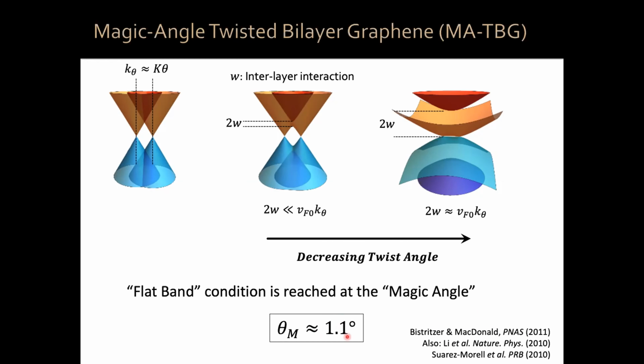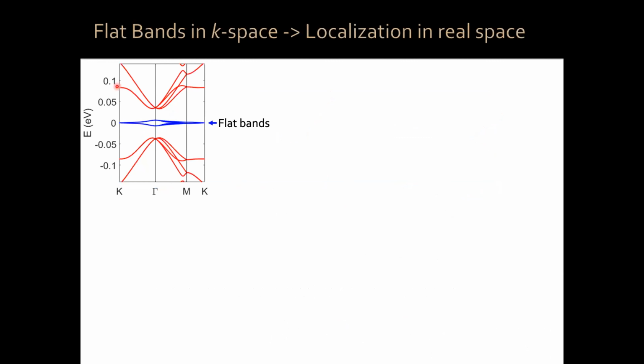Now, this is a magic angle for graphene on top of graphene. This depends on the materials. Yeah? Now, this is sort of a schematic. Let me show you an actual calculation. This is an actual calculation of energy versus momentum for magic angle graphene. Okay? These are the set of flat bands. And there are another set of remote bands. Each of these are called moire mini bands, okay? Due to the periodicity of the moire wavelength, you break up your energy momentum structure into a set of mini bands. In this case, spaced by band gaps from the flat bands to the more remote bands. These flat bands are the ones that we're interested in, okay?